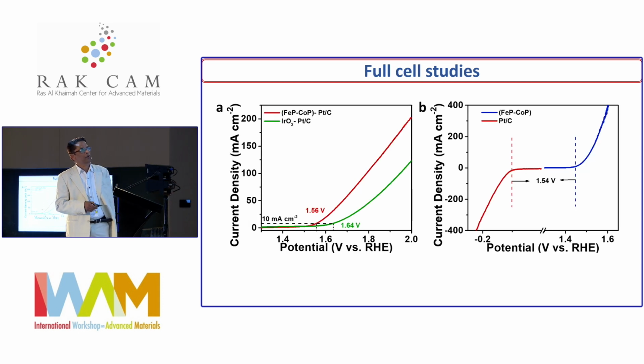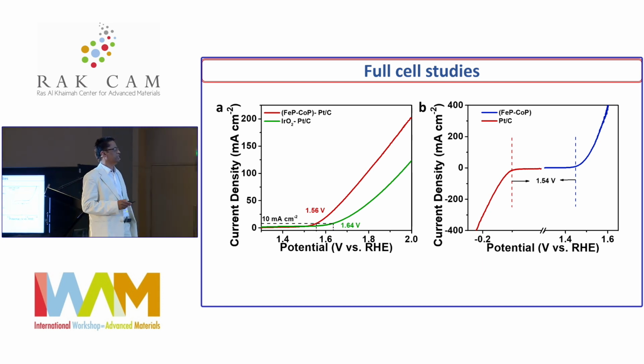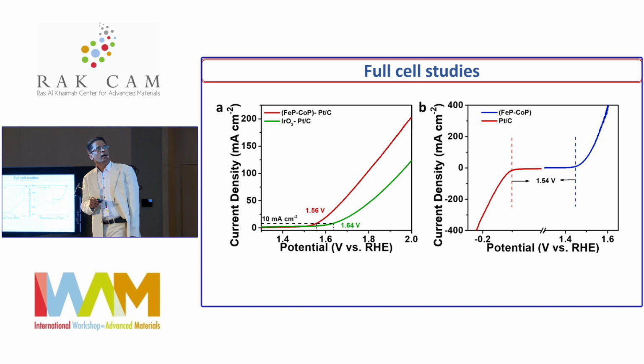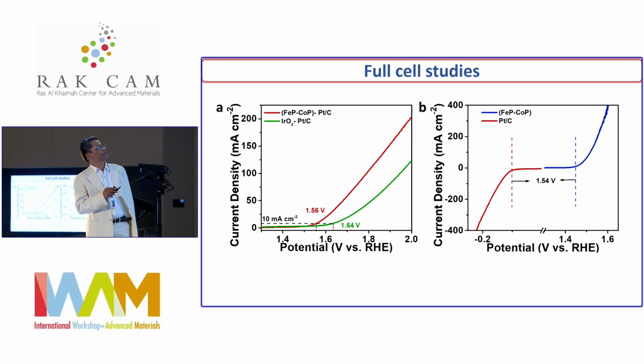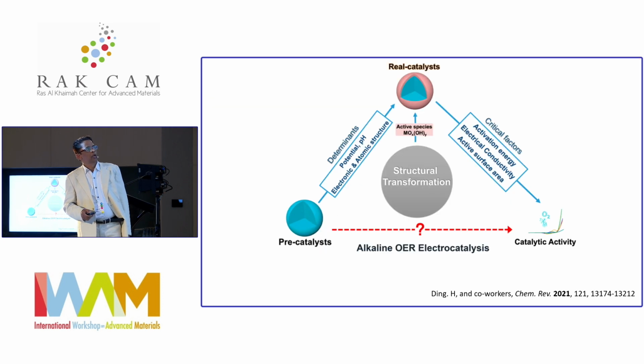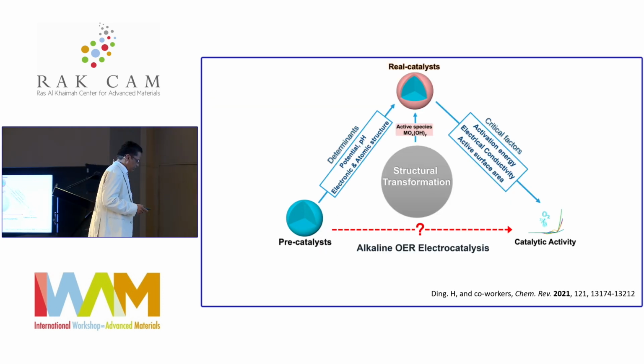And if you take that in a full cell potential study, it also gives 1.56 volt at 10 milliampere per centimeter square current density, with the FeP-CoP as a working electrode and Pt/C as the counter electrode. So we will be able to get 10 milliampere per centimeter square, and 1.56 volt will be sufficient to do that. And what is the species in this process?